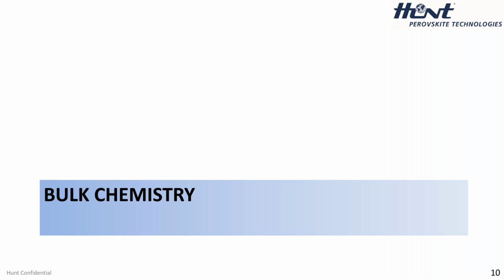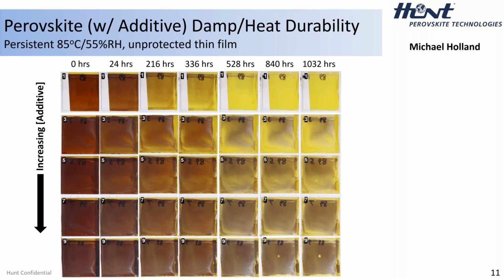So starting off with bulk chemistry, that's the one I think that most people focus on currently. And in our case here, we're utilizing formamidinium lead iodide. I'll make no secret of that. What's actually in it is where the IP lies. So in this case here, you can see it starts at the top as a pure FAPbI3 material that is loaded into a damp heat oven. It's sitting at 85 degrees Celsius, 55% relative humidity at 85 C. So this is a very nasty environment. And so we took our pure material, put it into this environment unprotected. There's no coatings, no encapsulation, no nothing.